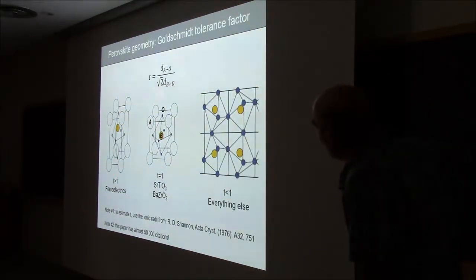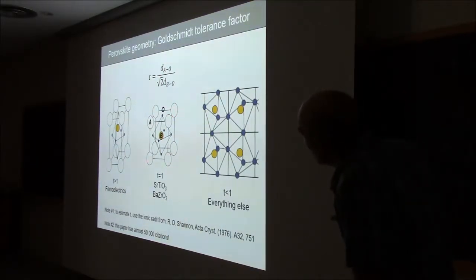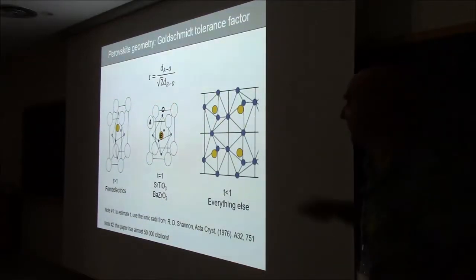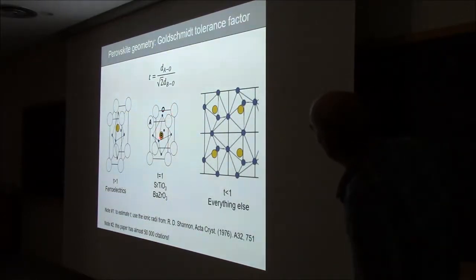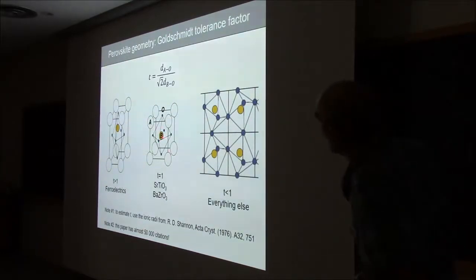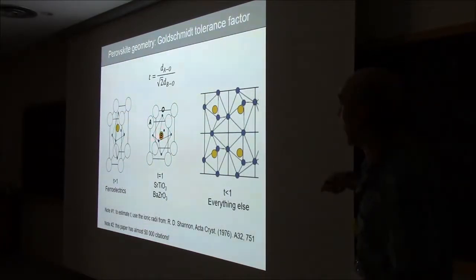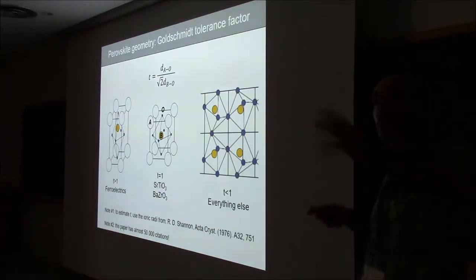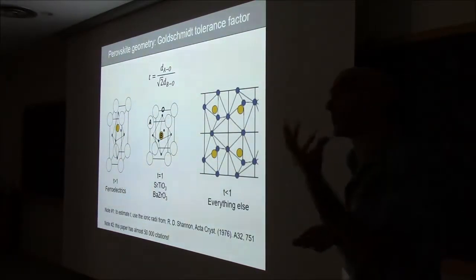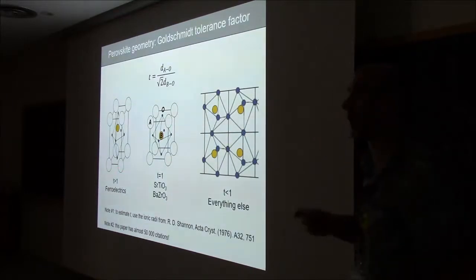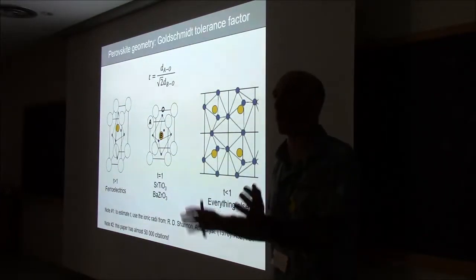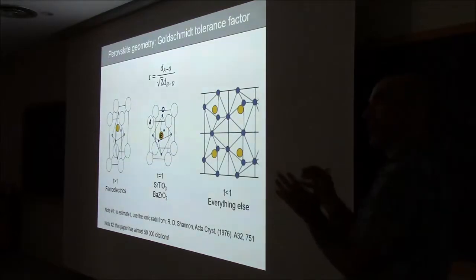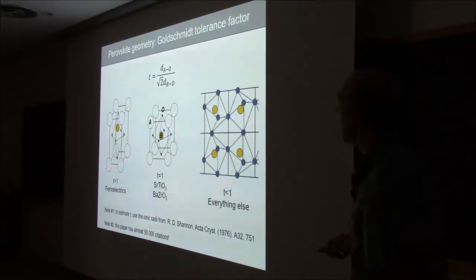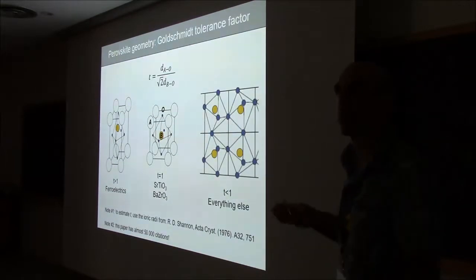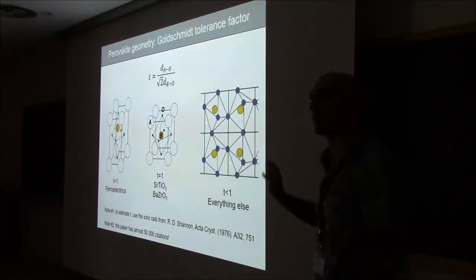Now, if t is bigger than 1, that means that this cage, the A site cage, is very big, which means that there's a lot of empty space for this B ion to rattle. It can rattle in any direction, and so you have a very polarizable unit cell. So if you have t bigger than 1, but not too big, because if it's too big then it's not even a perovskite, but close enough to t equals 1, just a bit bigger than 1, then you have a geometrically favorable situation for ferroelectricity.